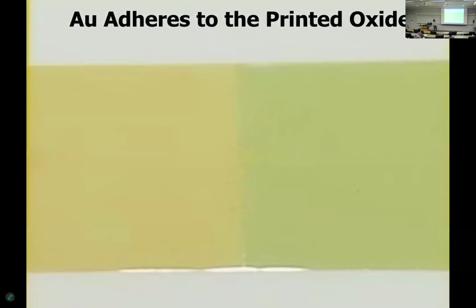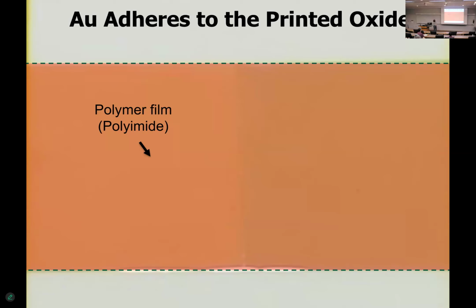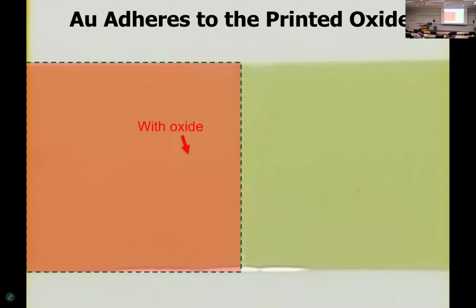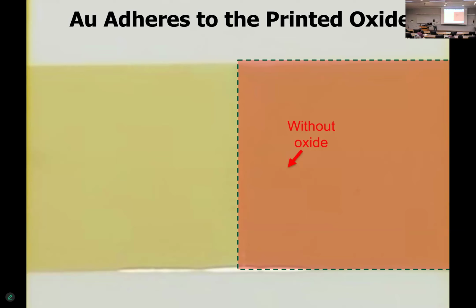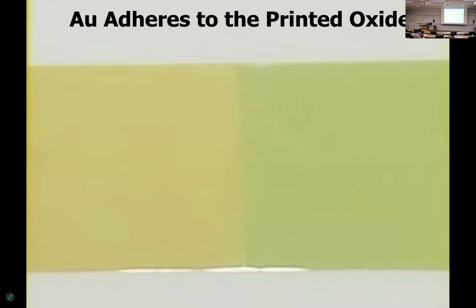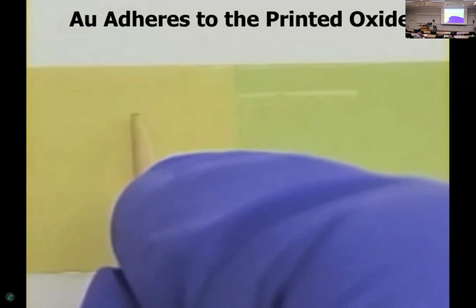It's not stuck. So let me show you again why this is so interesting. We deposited 4 nanometers of gold on polyimide. This is a material used for flexible circuits. And so it's got a yellowish color even before we put the gold on there. So here's our film. On the left-hand side, we deposit our oxide film, 4 nanometers of gallium oxide. And then over the entire sample, including where there's no oxide, we deposit the gold. And then we come in with a toothpick, and you can see it rubs right off of the polyimide, but it does not rub off of our film.